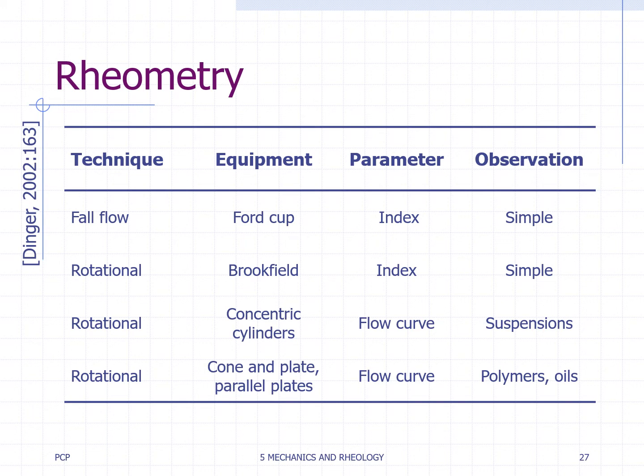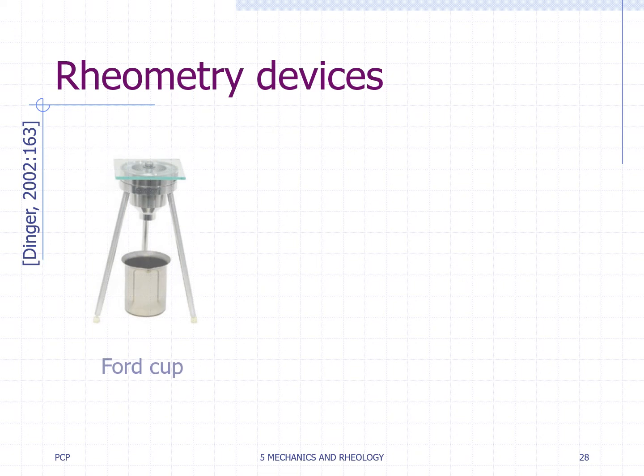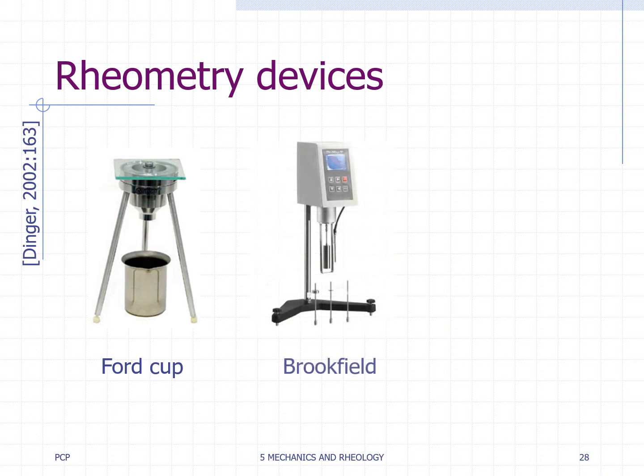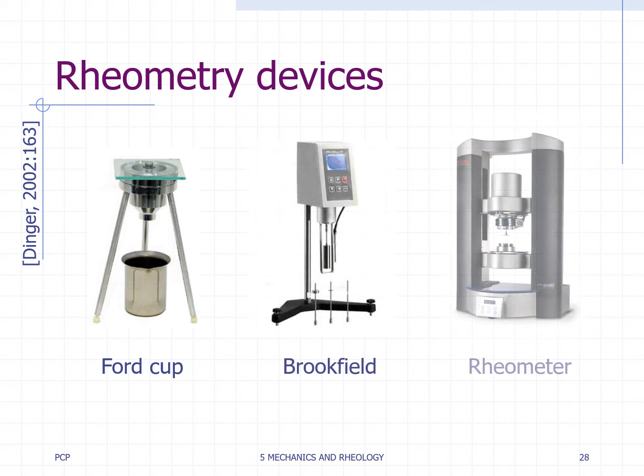High-precision shear instruments in which the test fluid is sheared under controlled stress or controlled rate conditions are termed rotational rheometers. Most rheometers depend on the relative rotation about the common axis of one of three tool geometries: concentric cylinders, cone and plate, or parallel plates. Here, we may compare simple rheometry devices such as a Ford cup and a Brookfield type viscometer with a complex advanced rheometer, in this case with parallel plates geometry.